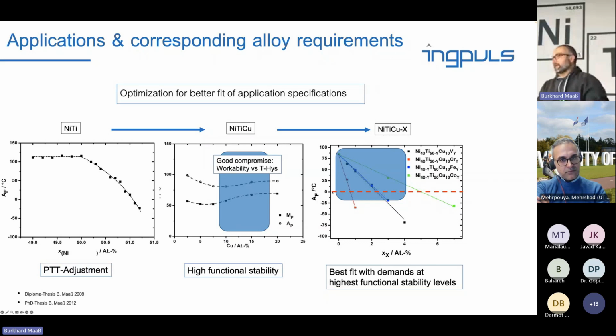Of course, this is just if we want to have an AF of 0, then I can do some interpolations, and then I know how much of these elements I have to put in. If someone comes and wants a higher AF, I can do this as well, of course. What we found out is that putting in iron and cobalt, which substitute nickel, provides very good workability, but the functional stability becomes very poor.